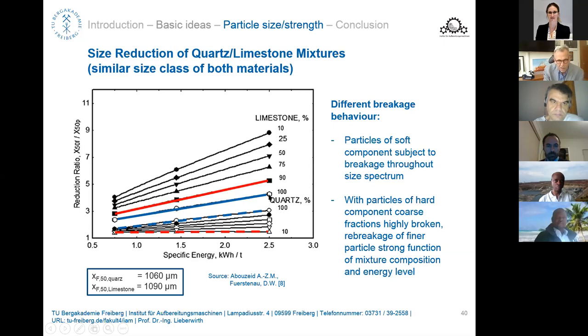What we could see here is pretty nicely that in case you are crushing the pure limestone or the pure quartz, you have these blue curves here. And the angle of the blue curves is pretty similar, the inclination angle. So if you have the pure material, just for the limestone, you consume more energy, and your reduction ratio will also be higher, or at the same energy consumption, your reduction ratio will be higher, put it this way.